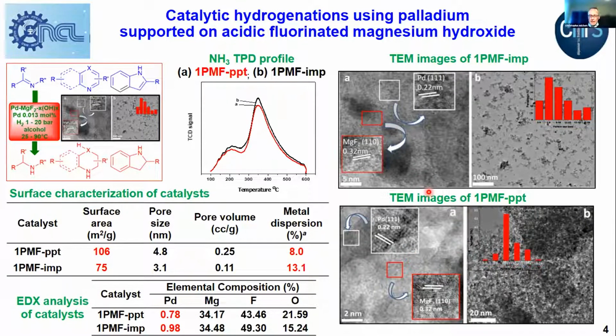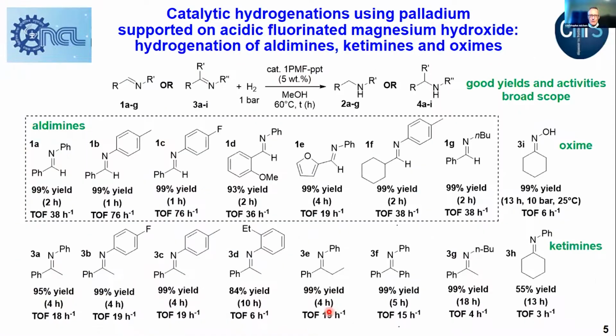We then switched to reactivity studies and application to hydrogenation. At first we studied the hydrogenation of various aldimines, and you can see that the reactions are quantitative in 1 or 2 hours with reasonable catalyst loading at 60 Celsius and 1 bar hydrogen. Substrates like oximes can also be hydrogenated, provided you apply 10 bar pressure.